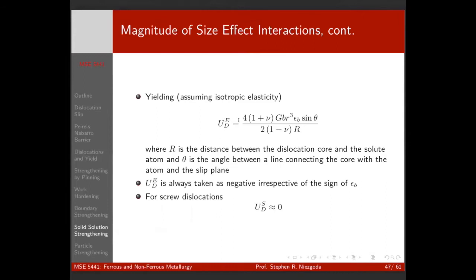This is our energy for an edge dislocation: R cubed, the strain parameter, the angle between the slip plane and the atom makes over the distance, and then Poisson's ratio is in here. This is like your dislocation core width term, right? And this is the general form. So the big thing, it's going to be G b times this strain term that are the important bits.